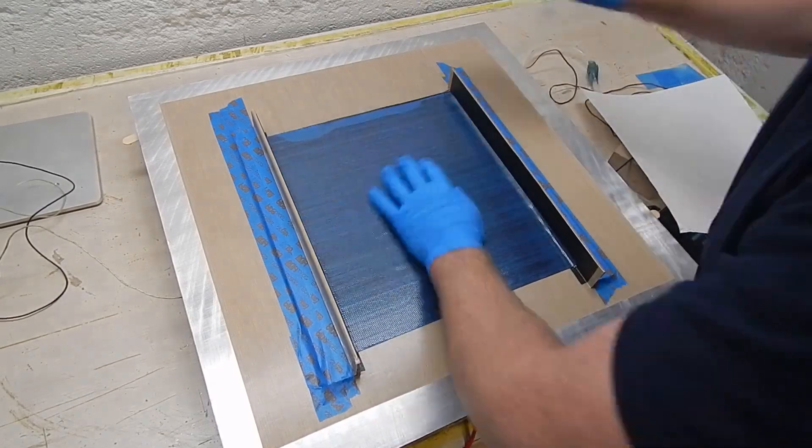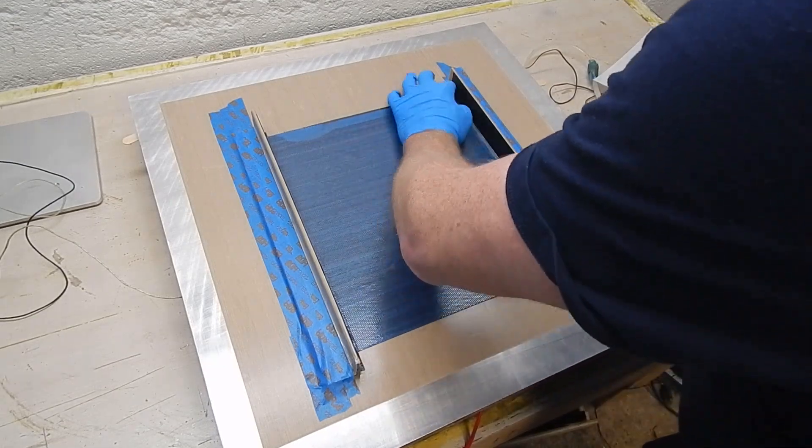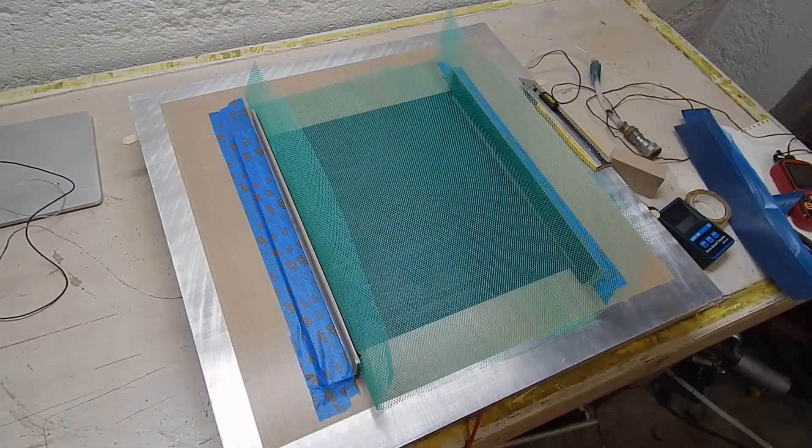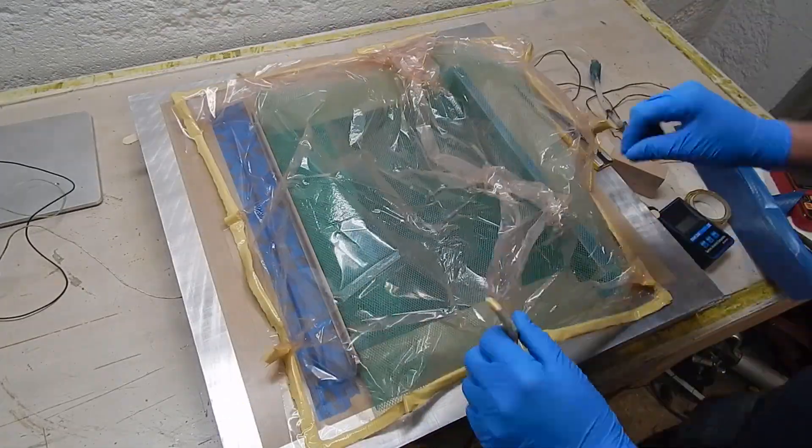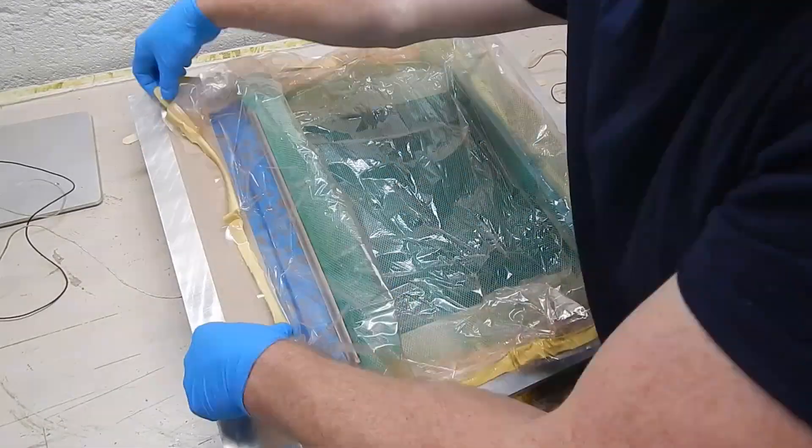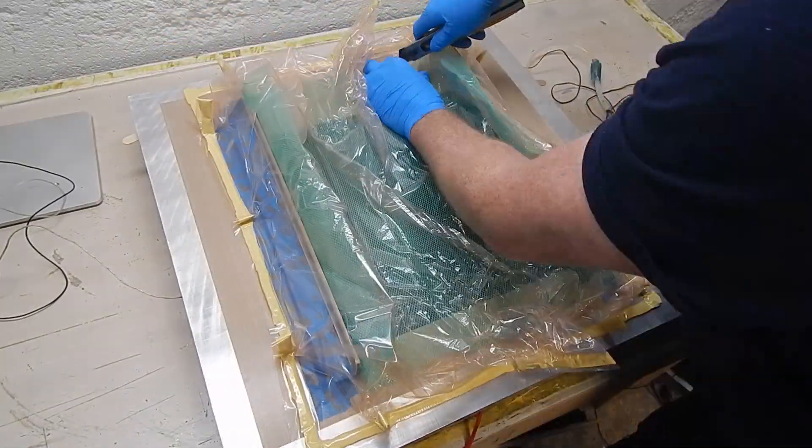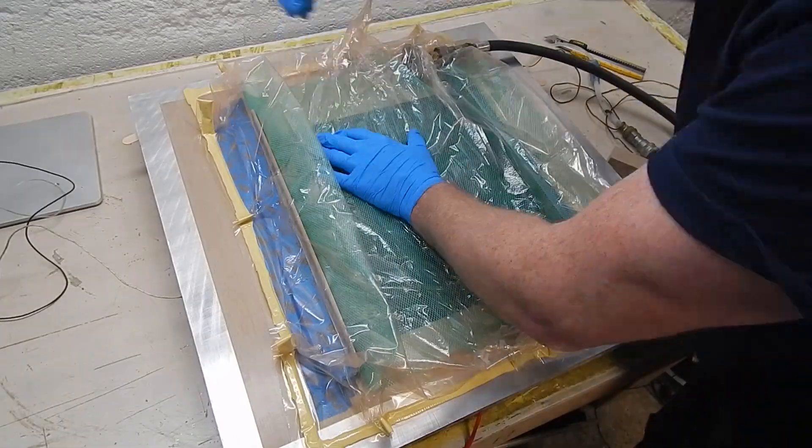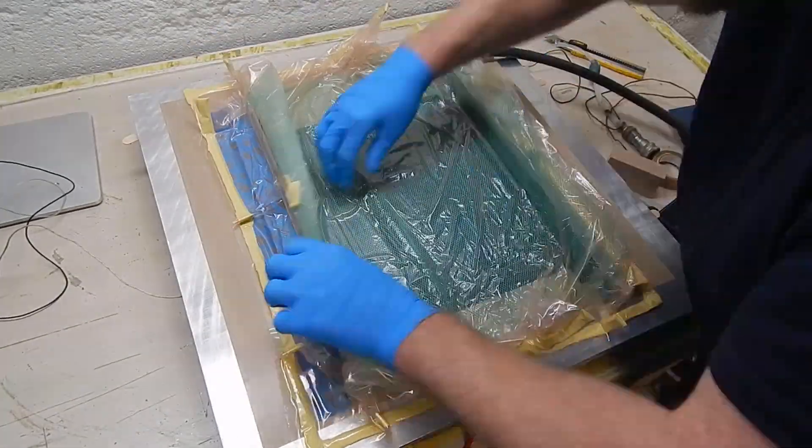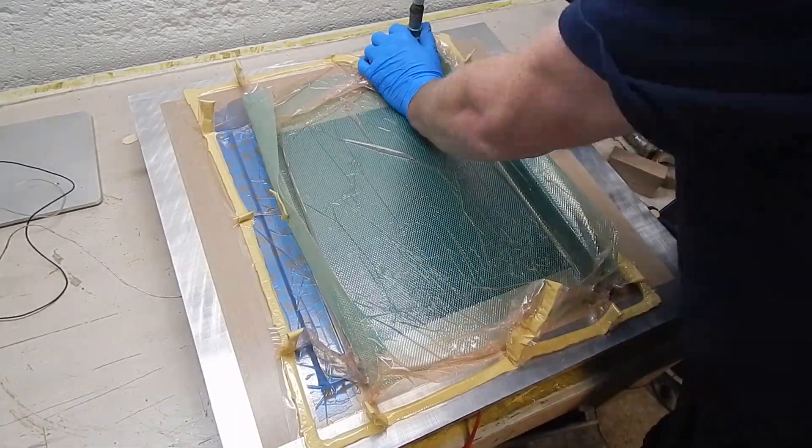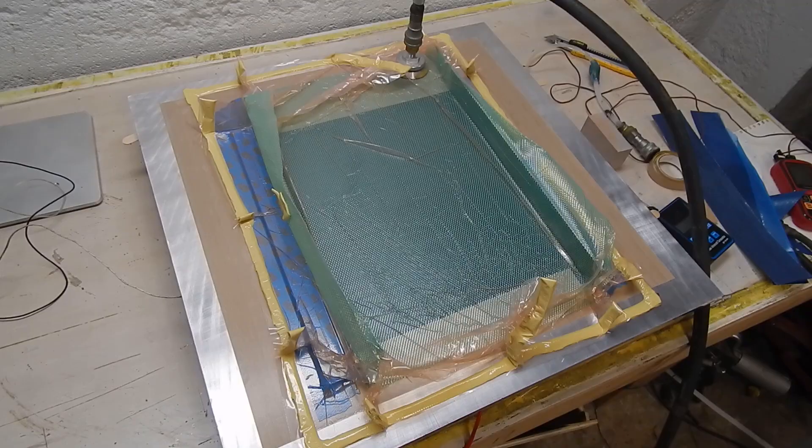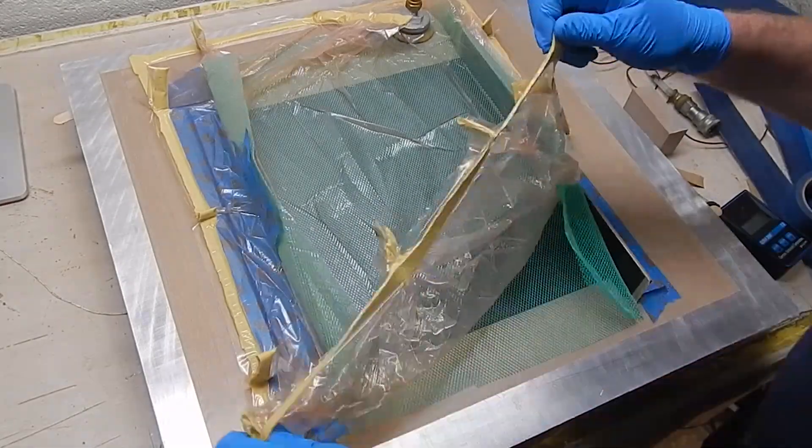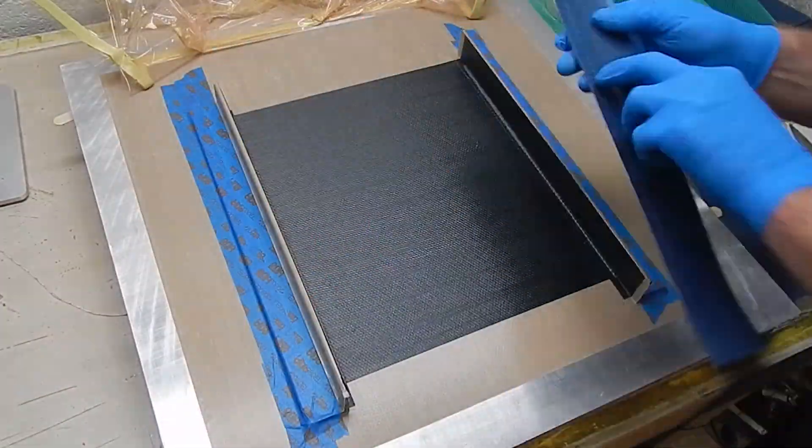So the first ply is, I guess you'd call it 90 or zero, depending on where you're starting from. And at this point I'm going to give it a quick debulk. This is a used vacuum bag from another job. You can see I've pulled it onto the Teflon so that I can make extra pleats. I'm just trying to not waste bag material. And for debulking, it doesn't need to be perfect really. It's better if it is, but it doesn't need to be. And after about five or ten minutes, I pull it off. Everything looks really nice.